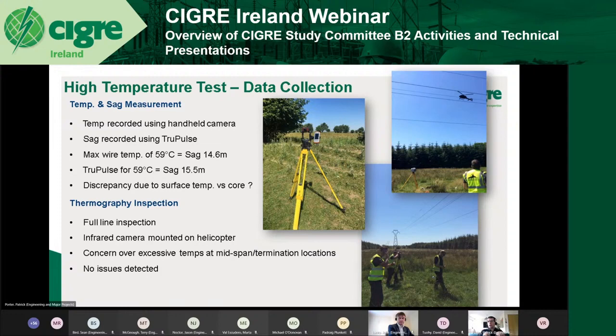The lads also then had a handheld infrared camera, which they would use as part of their line condition assessments for maintenance purposes and the like, and they were recording the conductor temperature using that handheld camera throughout the day also. But what we found during the day was, the first one being that we didn't get a temperature greater than 59 degrees with the handheld camera. And then when we compared that to the expected sag of the TruPulse device, and we had two separate data sets, they weren't really correlating, and we were getting some discrepancies.